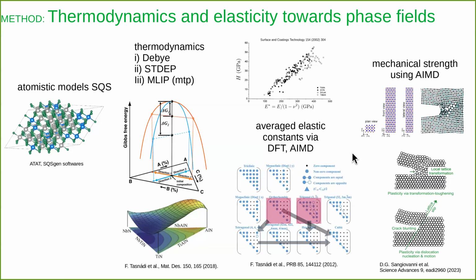Then we calculate elasticity for the alloys, and here I just want to mention that we calculate the average elastic constant. So it means that even if we have an alloy, we are aware that in the case of an SQS, where you have an alloy, you break the symmetry, and then you need some averaging technique to get the right elastic constant.